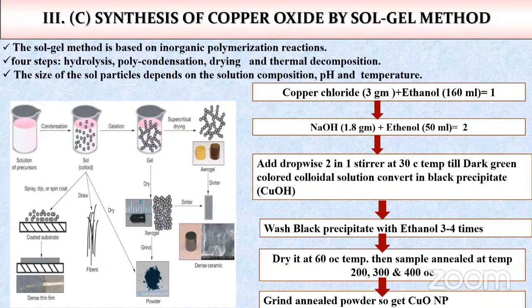Then it is dried at 60-degree temperature, and this sample is annealed at various temperatures, that's 200, 300, up to 400. And then finally, whatever black powder is there is ground, and we get copper oxide nanoparticles. Next.